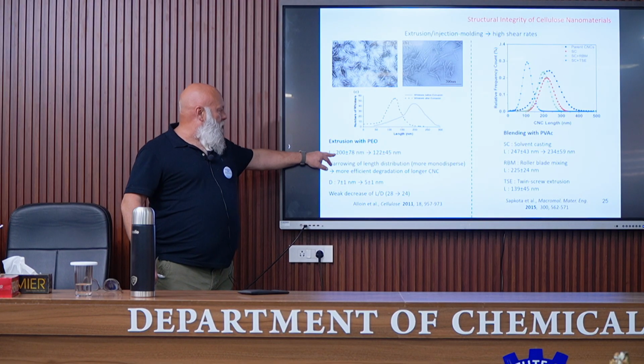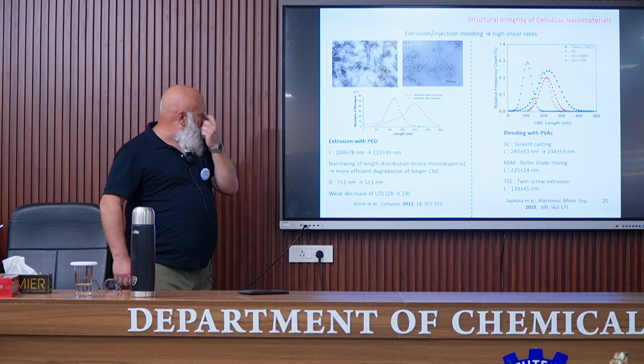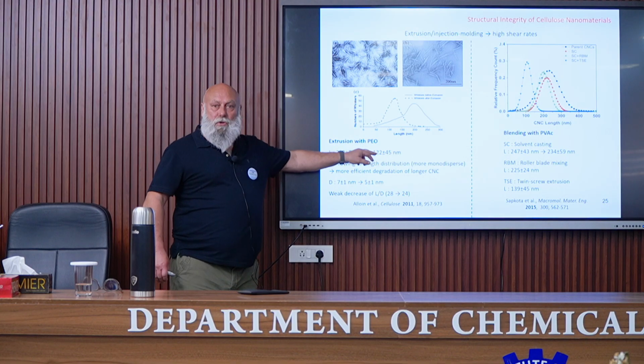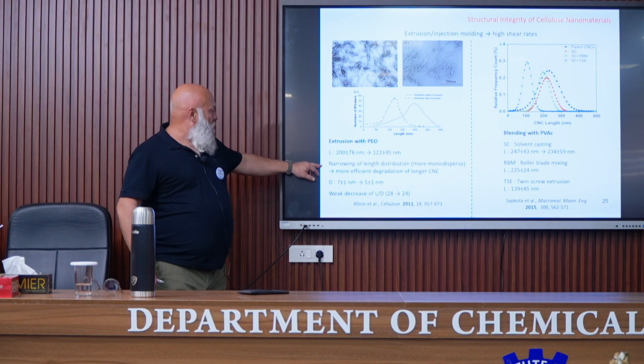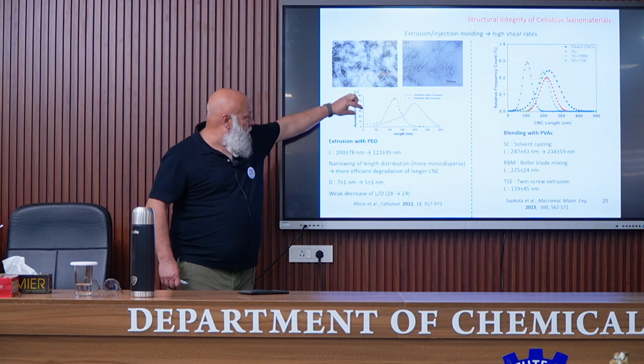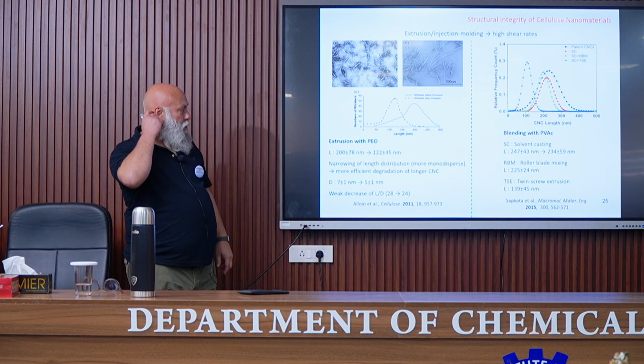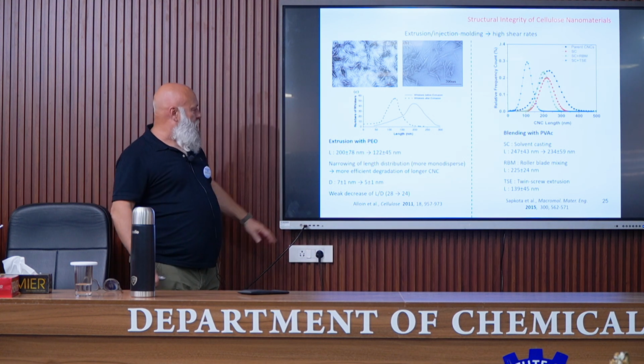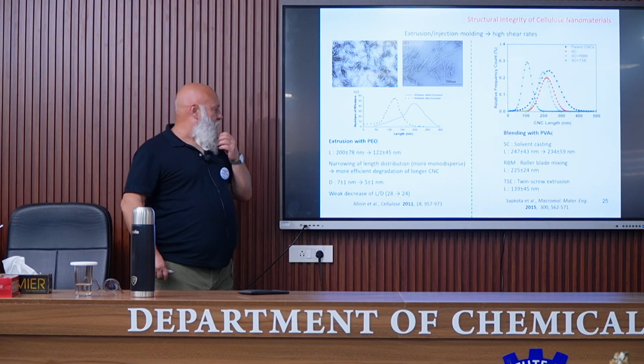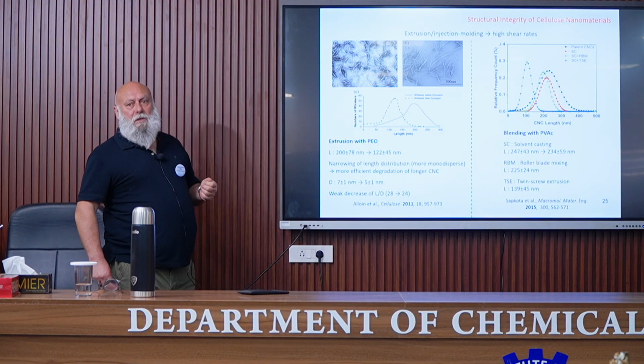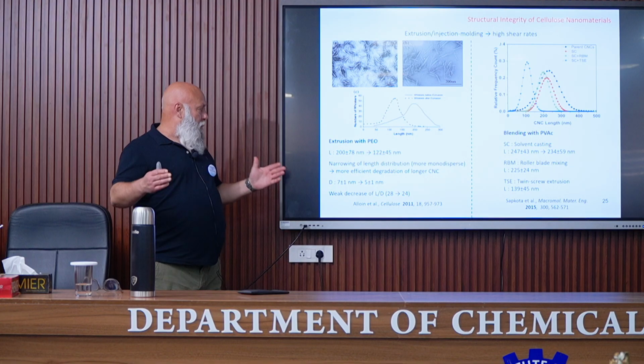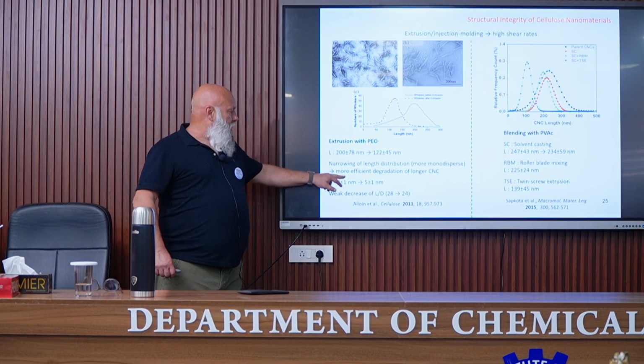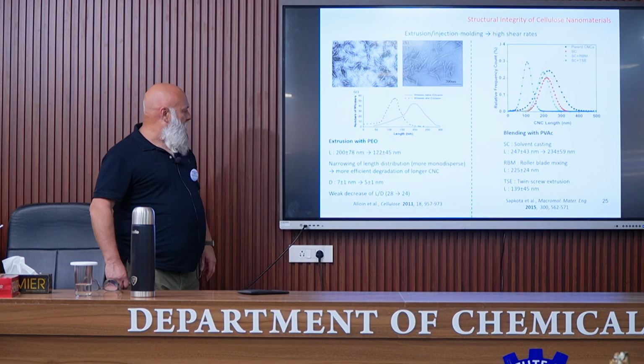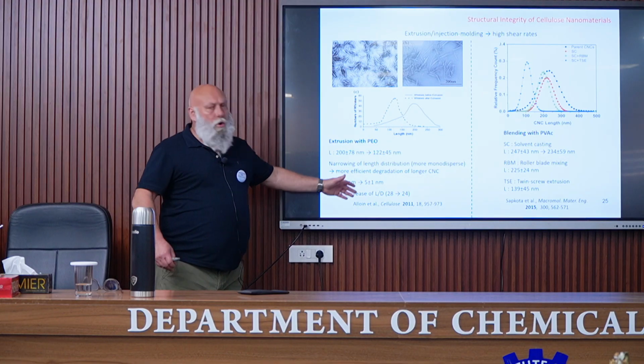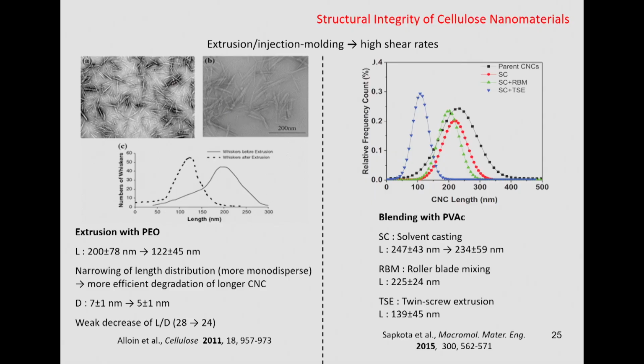Initially, the average length was 200 nanometers. After extrusion, 122. We can also observe a narrowing of the length distribution, it becomes more monodisperse, just due to the fact that there is more efficient mechanical degradation of longer nanocrystals. The diameter also slightly decreased, meaning that globally the diminution in the aspect ratio was limited.